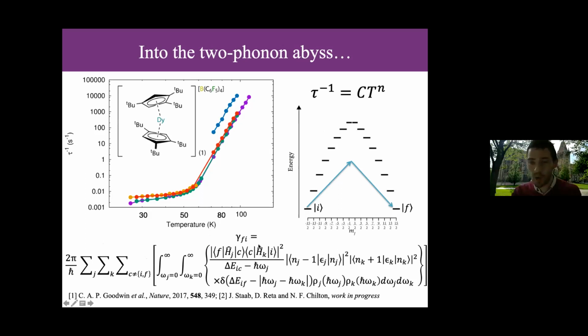Of course, it's far more complicated now. You have 2 phonons, I and J, you have 2 occupations, you have 2 density of states, you have a different delta function here. So conservation of energy is now the difference in the energy of these vibrational modes must match the difference in the energies of I and F. And then you have to integrate over all possible vibrational energies, which makes this far more complicated. And there are lots of subtleties in how you do this in practice.